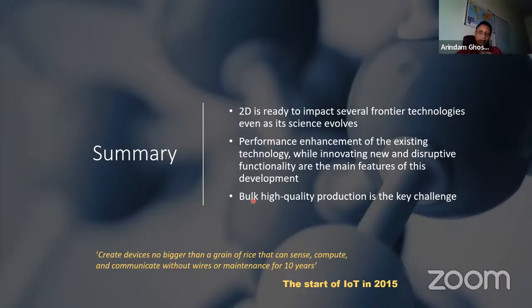There are several techniques. Ultrasonication, as you just said, is the most popular technique for reducing the size from the bulk material into nanosheets. That's what most people today use for large-scale production. But ultrasonication alone is not enough. If you want a high-efficiency, large percentage yield of two-dimensional material, then you need to make some other arrangements. For example, you need to put them in a solvent with similar surface energy, or do some other things. So there are various variations of these techniques, ultrasonication included, that are being pursued at this point in time.